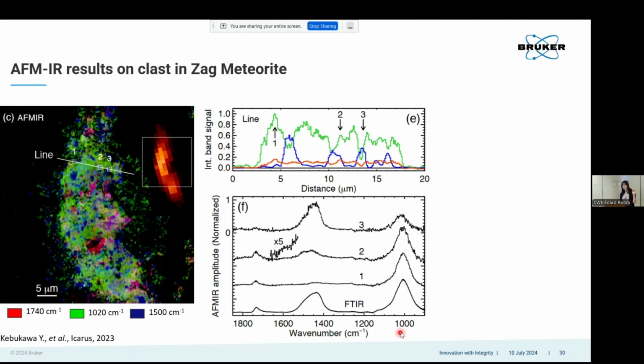But so what you're seeing looks like an average of the entire material. Whereas we can now go and see the areas where, okay, carbonate is higher, where PAHs are higher. And if you kind of ensemble all of those and take an average of all of them, they look like the FTIR spectrum. So you're getting the secondary confirmation of what you're seeing on the nanoscale with the macro scale.